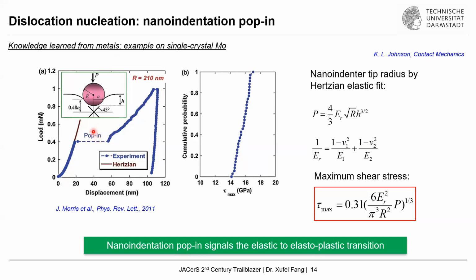And in metals, it has been well established that this pop-in event actually corresponds to dislocation nucleation, meaning that originally underneath the sample, underneath the indenter, we have a dislocation-free region, and this popping event correlates to the dislocation generation or nucleation. And of course, there are quite a number of equations to compute the stress level corresponding to the specific point when this instability occurs. As you can see, the maximum shear stress required for this popping event to happen, or the so-called dislocation nucleation, in this case, is around 14 to 18 gigapascal.